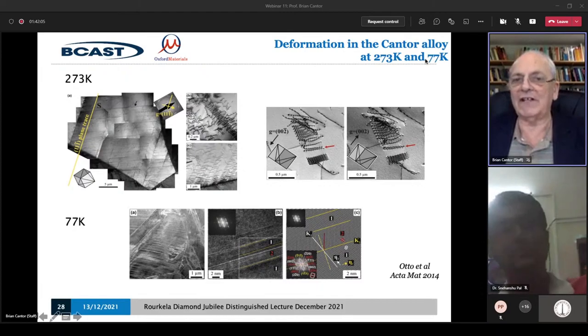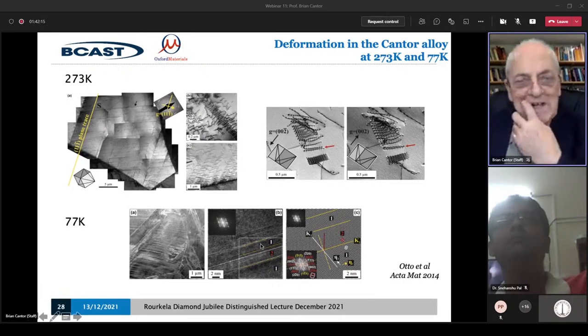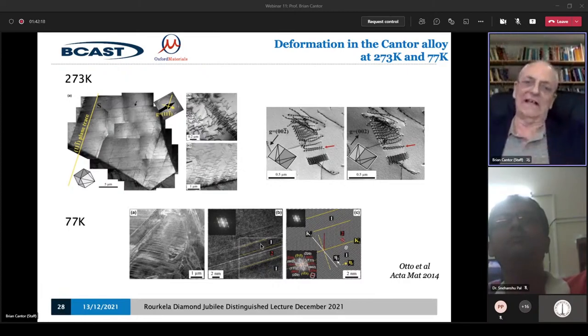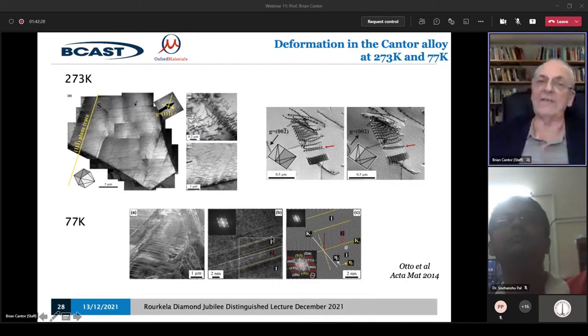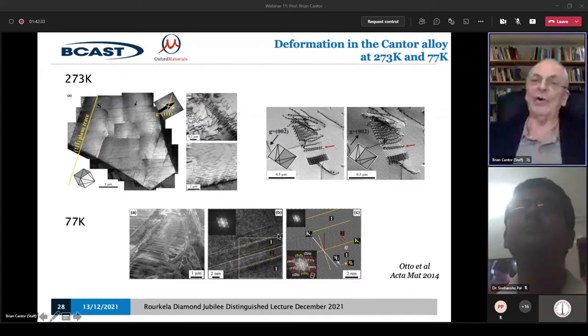And at low temperatures in the Cantor alloy, the properties are even better, as shown here in low temperature deformation, because you form twins. Twins are a more complicated version of stacking faults. They're related to stacking faults. And if the stacking fault energy is low, then the twin energy is low. So you can indeed tailor the twin energy to make deformation twinning a much more common deformation mode. You can also tailor them to make what's called transformation deformation, that's to say the formation of HCP from FCC.